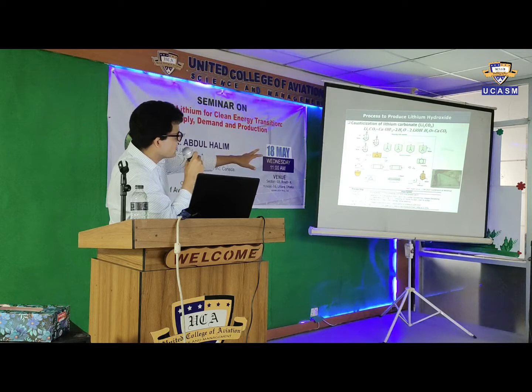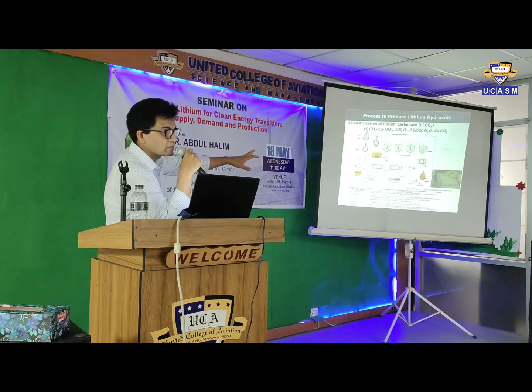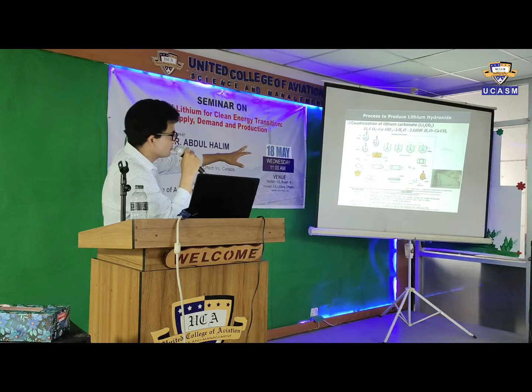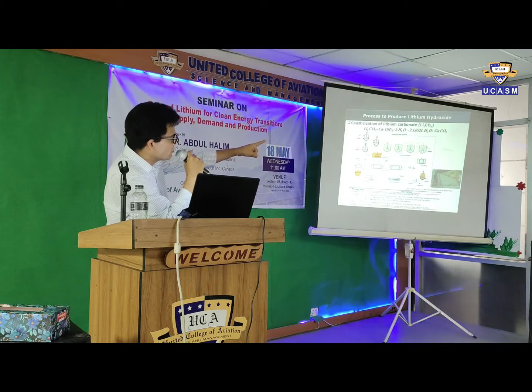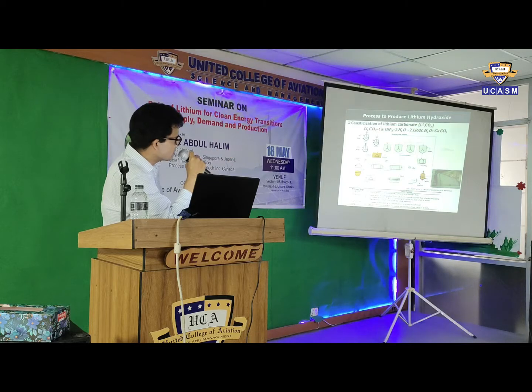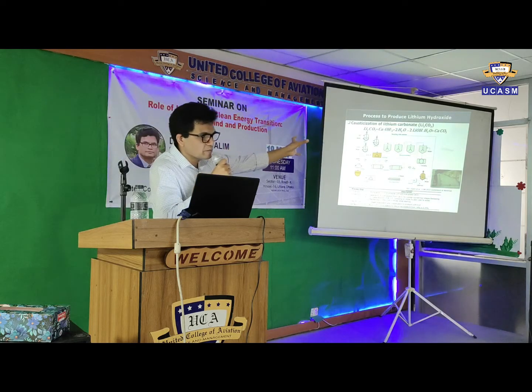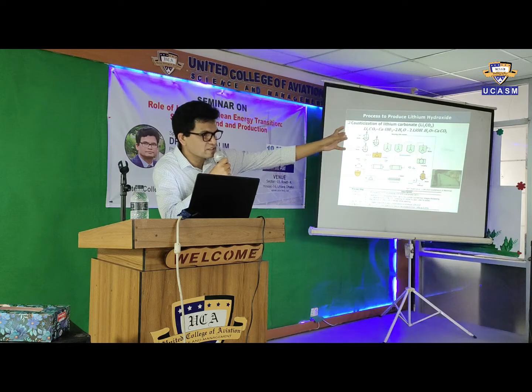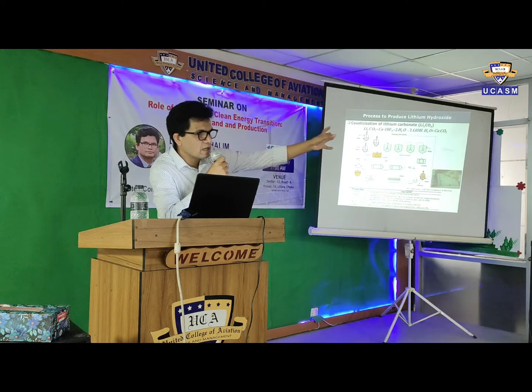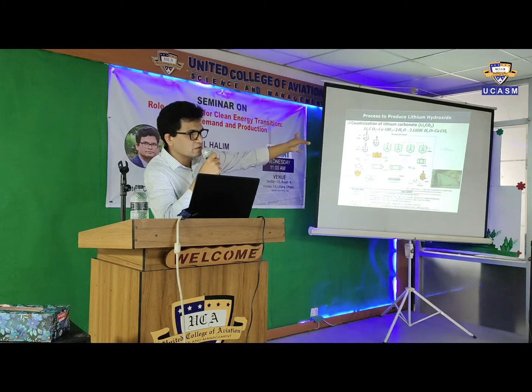This is the process currently used in the industry to make lithium hydroxide from lithium carbonate. We use calcium hydroxide with water to make lithium hydroxide monohydrate. That is the initial product we use for the battery industry. And there is a chemical byproduct, calcium carbonate. So we are using lithium carbonate, and producing calcium carbonate and lithium hydroxide.